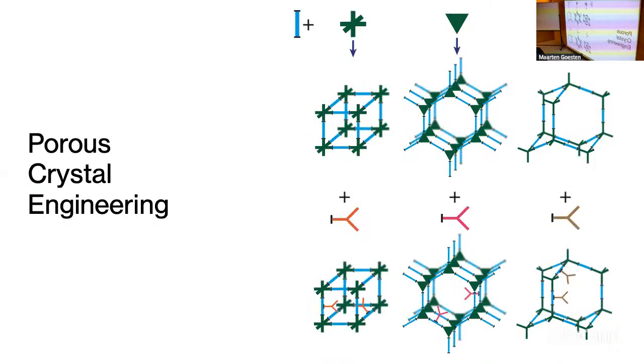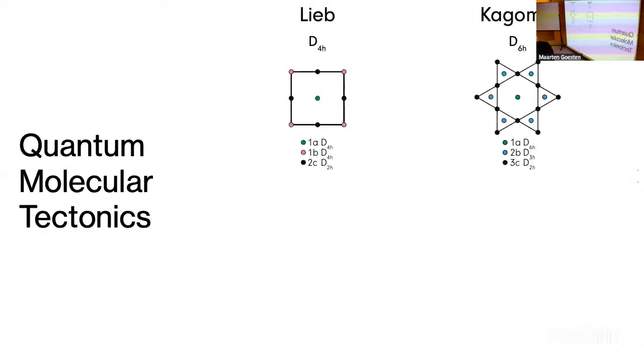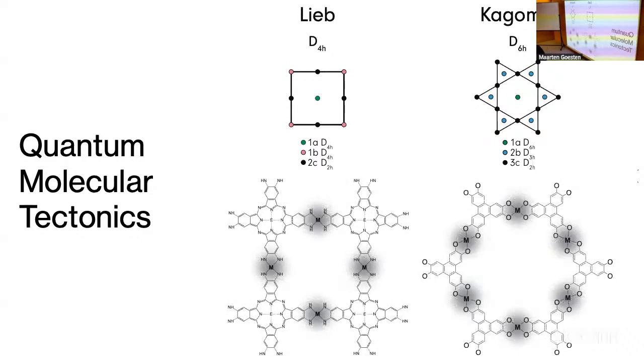One other thing that is great about them is that they are porous. Whenever there will be some time today, I will show you some very preliminary results of something. But what we can do with porous space is that we can actually post-functionalize it. So we can first make the MOF, or actually we can use a ligand, a building block which contains a specific functionality, and then we can self-assemble the system. Now, if you look at the Lieb lattice and the Kagome lattice, due to some fantastic chemists, we actually have synthetically available metal organic frameworks that will give you these space groups and all the operations and all the symmetries that we need.